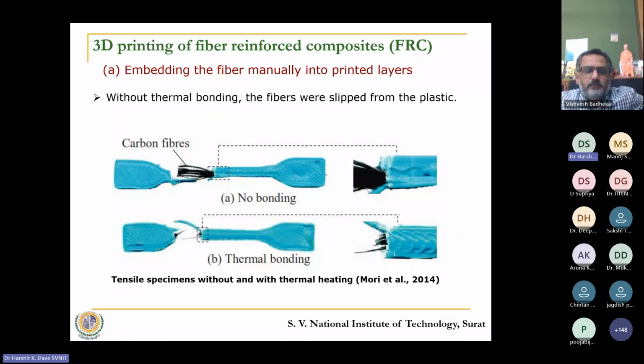So it means that the polymer breaks at its own strength without having any support from the carbon fiber. However, when this part is put up for post-processing and thermal bonding is carried out, we observe that there is an even mixture between the layers of polymer and the fibers. So when the testing of such a part is attempted, we observe that the fibers do not allow the polymers to break. The polymer layers are not broken because they have integrated with the fiber. So this goes on till the fiber loses its strength and the fibers also break. So we see from figure B that when sufficient load is applied so that the fibers can break, till then the strength of the polymer is extended.